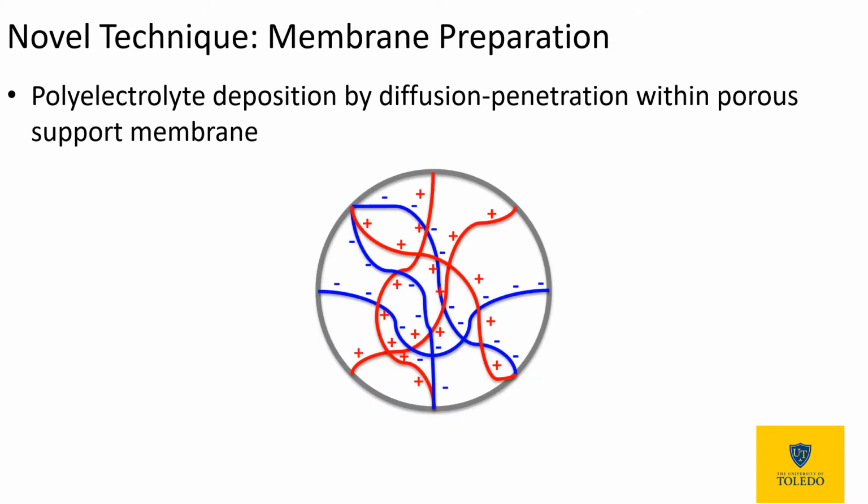The intent of depositing the polyanionic and polycationic polymers into the membrane pore was to create a structure such as that you see here. This is a cross-section of a pore looking from top to bottom, in which we have ionically cross-linked polymers. But the cross-linking leaves free many different charge sites along both polymers, and it's these charge sites that we were hoping would lend the charged mosaic character to it, that would allow a salt ion to dissociate and then diffuse or move by convection through the pore of the membrane from site to site within the charged mosaic structure.